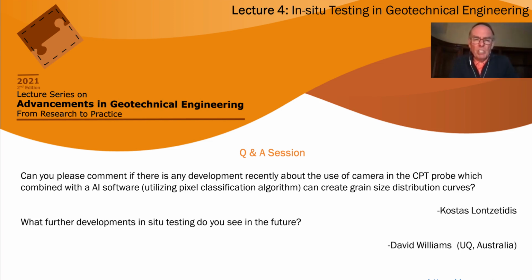Now, as for in-situ testing, I got into in-situ testing 40 odd years ago, and I got into it because I realized that traditional drilling and sampling was inadequate to really tell us enough about the material, and partly because many of the samples were disturbed. So although we would do lab testing, we were doing lab testing on predominantly disturbed samples. And with the drilling, we were only seeing small portions of the profile, not the whole profile. So I got into in-situ testing, and I very quickly studied the CPT, the vane, the SPT, the flat dilatometer, the pressure meter, and the screw plate, etc. And then realized that the CPT was the one that probably had the most growth potential.